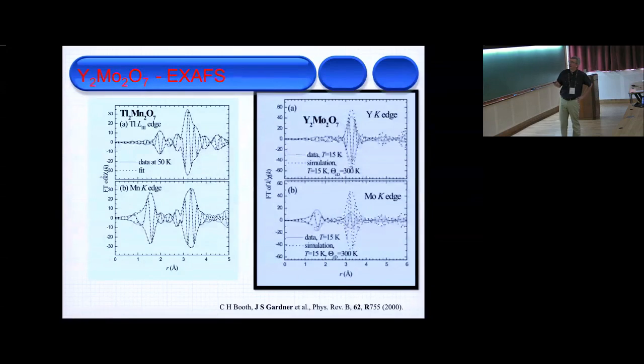If I look at a pyrochlore which is conventional, that has a ferromagnetic transition or so, with this technique called XAFS, the data is the dashed lines in the middle with the dots, and the model is the envelope and the lines in there. In this system, our pyrochlore model fits it beautifully. In our glass, it doesn't, especially on the molybdenum edge. And to a first approximation, as someone that doesn't do XAFS, that's all I will say.